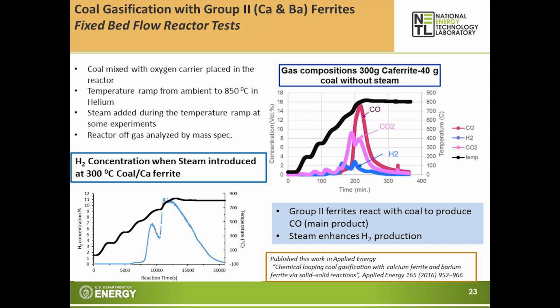Okay, we conducted bench scale fixed bed flow reactor tests to evaluate this concept. Here we mix coal with the oxygen carrier, this is calcium ferrite, and place it in the reactor, and we did a temperature ramp from ambient to 850 C in helium. And in some tests we also added steam during the temperature ramp.